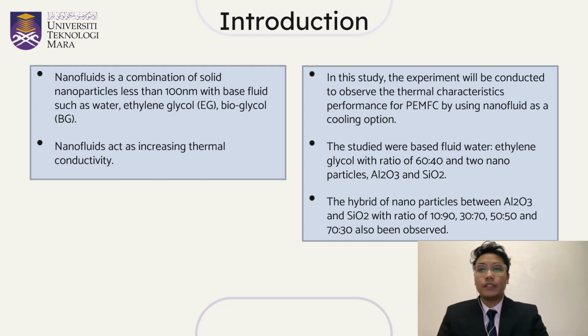The results show that the thermal conductivity of a suspension of nanofluids is significantly higher than that of the equivalent base fluids. In this study, the experiment will be conducted to observe the thermal characteristic performance of PEMFC by using nanofluids as a cooling option. The study will use a base fluid of water and ethylene glycol with a ratio of 60-40 and two nanoparticles, Al2O3 and SiO2. The hybrid of nanoparticles between Al2O3 and SiO2 with ratios of 10-90, 30-70, 50-50 and 70-30 is also observed. The experiment is set up with 0.5% concentration of nanoparticles and the operating temperature of the channel is set at 60 and 70 degrees Celsius.